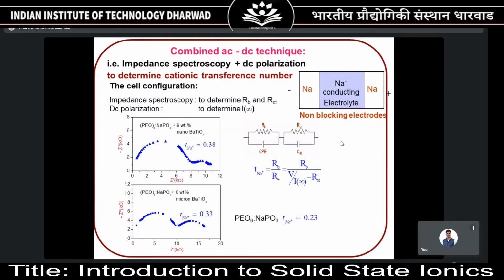From where did that resistance increase? Because of polarization of the ions. So here what we do is, we also calculate I infinite, that is the polarization current, and determine the transport number of sodium ions. So the percentage of sodium ions which are mobilized in the matrix.